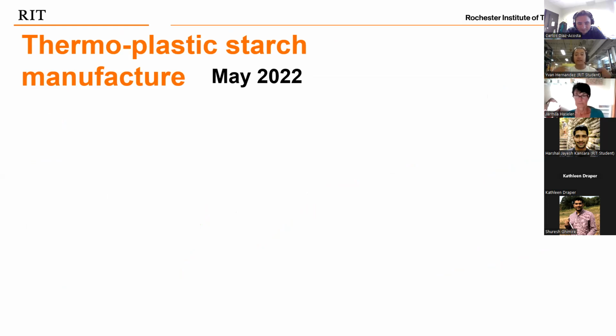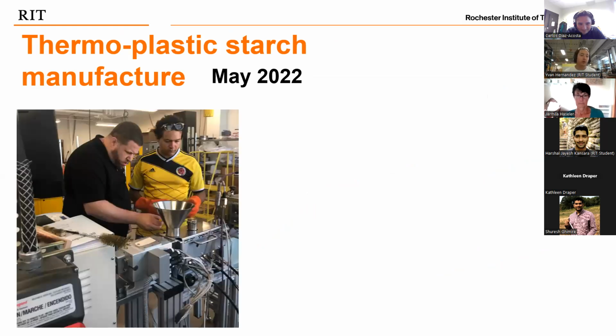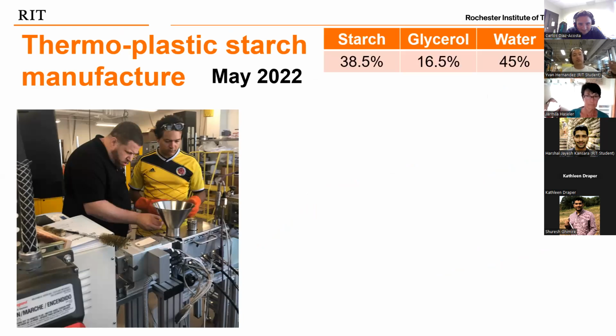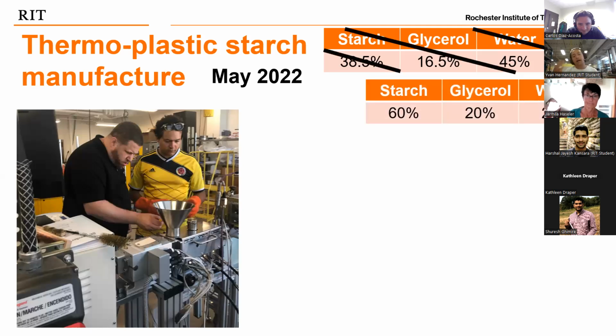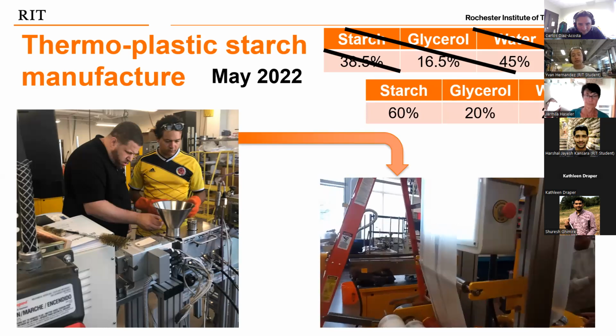So how could we scale it up? Make a field-worthy sample with that thermoplastic starch. And the problem is that I cannot bake during 40 hours straight. So I needed to find a way to actually manufacture that thermoplastic starch in a more industrial setting. Luckily, we acquired a twin screw extruder that allowed us to try different mixtures. And so I tried our mixture that had a lot of water, but sadly that didn't work. So I had to change a little bit the mixture, and I was able to finally use it in our blown